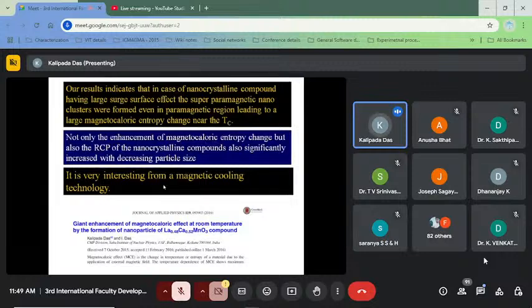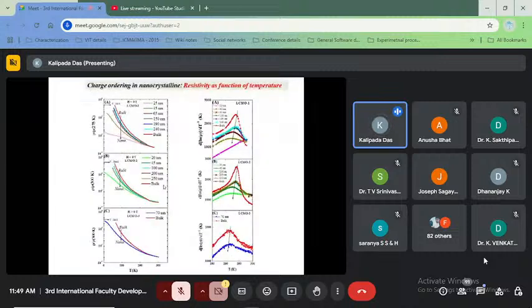So from this study, we conclude that in a single antiferromagnetic charge ordered material, we can still enhance magnetoresistance and magnetocaloric effect systematically. Now, what will be the magnetoresistance? To study the magnetoresistance, we have measured the resistivity as a function of temperature for all sets of nanoparticle. And we see that with respect to the bulk counterpart, in all cases, with reduction of the particle size, the resistivity value is reduced. But charge ordering is still there. In the nanomaterial, charge ordering is still there, but the resistivity value is reduced.